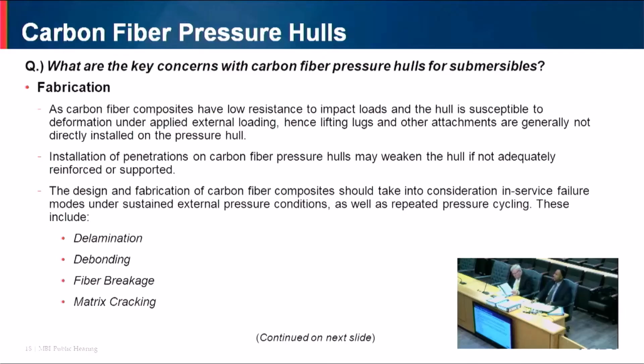Now, carbon fiber composites have a low modulus of elasticity, they have low shear strength, and they are brittle materials with low impact strength, okay? So they have very low resistance to impact loads, and the hull is susceptible to deformation under applied external loading. Typically, lifting lugs and other attachments are not directly installed on carbon fiber composite pressure hulls because they cannot withstand localized loading, and they tend to deform under localized loading. Then if you install penetrations on the carbon fiber composite pressure hull, that means you have to make openings in the pressure hull. That will weaken the pressure hull because the main load-bearing member in a composite is the carbon fiber strands. So if you cut the strands to make an opening, you're going to weaken the pressure hull. So reinforcement of the openings is very critical. And if you don't reinforce it, you can have stress raisers in the vicinity of the opening, and that can lead to cracks and failure of the pressure hull, okay?